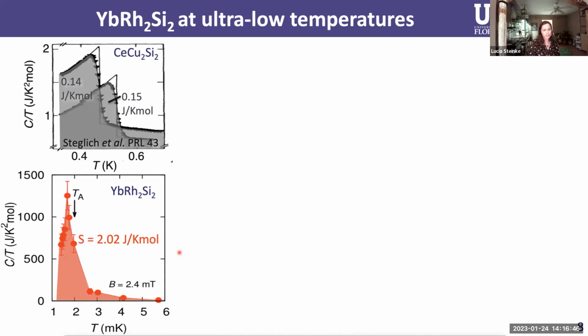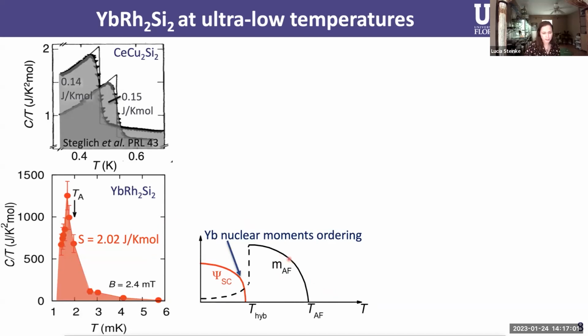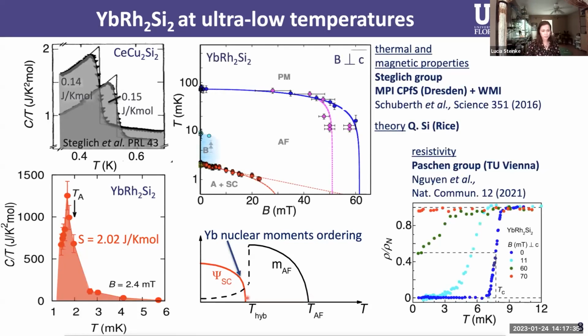And it is so large that we could not explain this transition with anything only involving conduction electrons. So it couldn't just be a superconducting transition. And it turns out what happens is, in addition to there being an antiferromagnetic phase, there is another type of magnetic order happening, and that involves nuclear moments, same moments that we use for cooling, on the ytterbium side. So there are ytterbium isotopes that have nuclear moments, and when they order, they compete with the antiferromagnetic phase and weaken it enough that that allows for superconductivity. So in other words, the nuclear moments are actually acting like another tuning parameter, pushing the system closer to a quantum critical point. And with all of that data combined, we are finally able to complete the phase diagram of ytterbium rhodium two silicon two at ultra low temperatures.